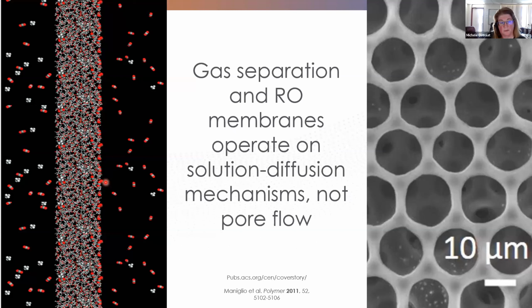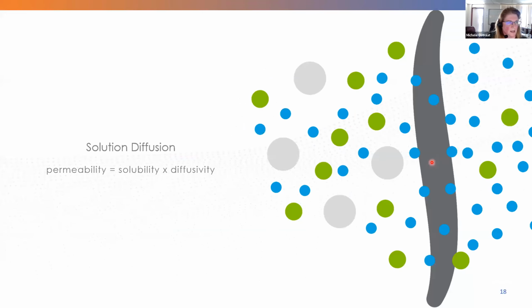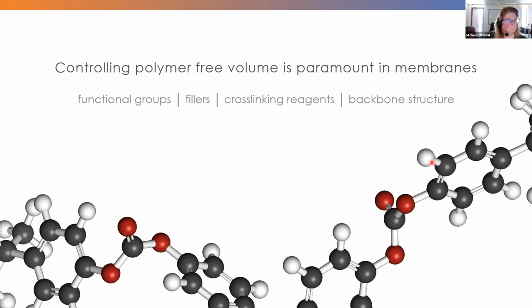Typically, a gas separation as well as reverse osmosis membranes operate on a solution diffusion mechanism, not on pore flow. For people who may not be in the membrane area, I think conceptually a lot of people think that membranes operate on pore flow, where you have a certain pore size, for example, and a molecule or a particle that's too big to fit through the hole doesn't go through the membrane. But these gas separation membranes operate on a solution diffusion mechanism, which is quite a bit different. This works by having materials not just be separated out by their size, but also by their ability to condense onto and into and then move through these membranes.